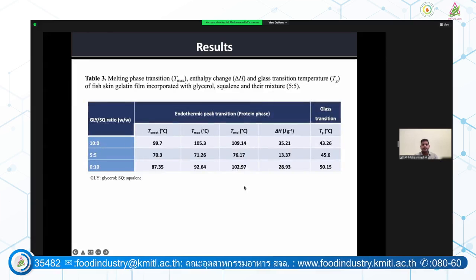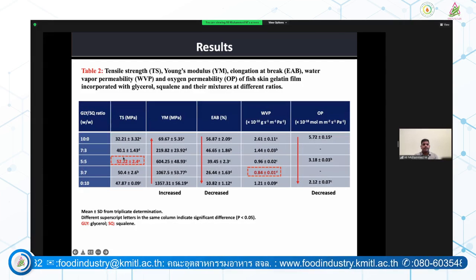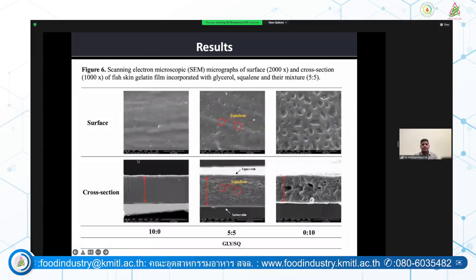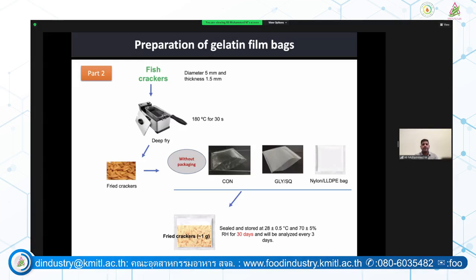And based on this, we have selected the film of maximum tensile strength to test the storage studies. We have used fried fish crackers, as we found that the squalene incorporated film has lower oxygen permeability. And we selected the fish crackers to test the oxidation stability of the stored sample. So here we have taken the packaging with just glycerol incorporated films, squalene at the ratio of 5:5 incorporated films, and the commercial nylon or LLDPE bags.